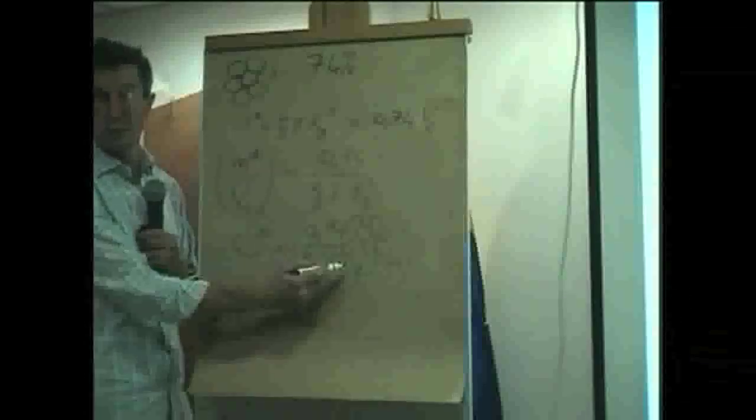Okay, of course, you have here the molecular weight, but be careful. The molecular weight is also inside Rg, because Rg is a function of the molecular weight. Okay, here I told you we are in good solvent condition. In good solvent condition, we know that Rg is proportional, a constant, times the molecular weight to the power 0.6, that means 3 divided by 5.